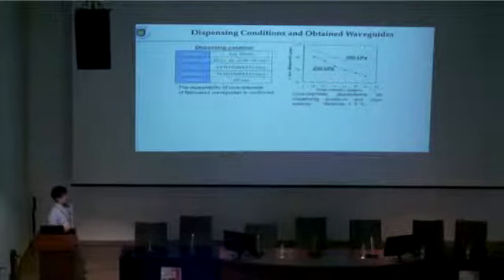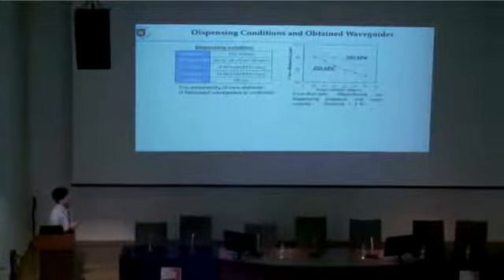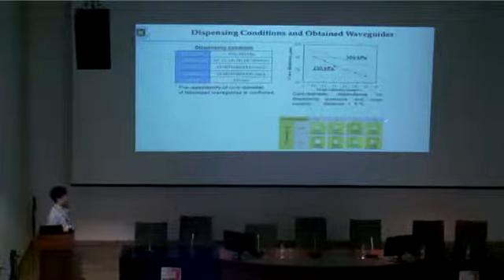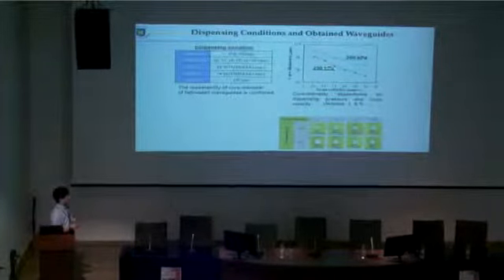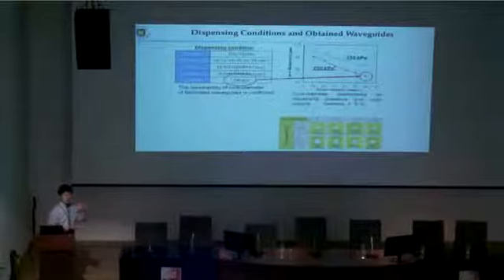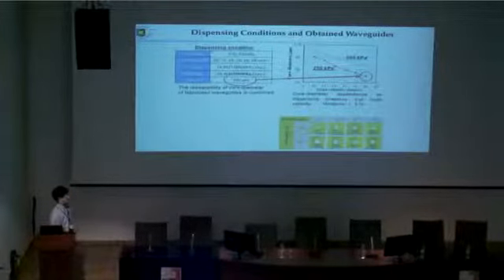You can see these parameters, scan velocity and the core diameter. In this case, we used 2 different dispensing pressures. From this chart, you can see that with decreasing dispensing pressure, we can obtain a thinner core diameter. And you can see circular cores are obtained this way. And with increasing scanning velocity, it is easy to imagine that we can also decrease the core diameter. And it is surprising that from a 190 micron inner diameter needle, we could obtain almost 60 micron core diameter by just adjusting the dispensing conditions.